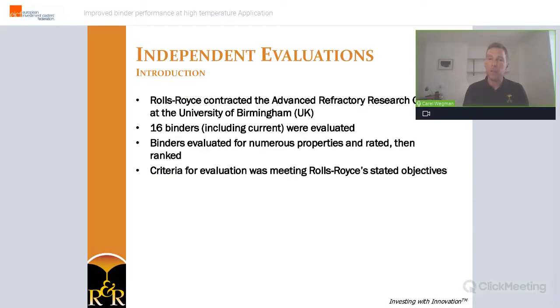So at this stage, we finalized all our in-house testing and we were comfortable that EHT would make a viable candidate for Rolls-Royce's new binder, and we submitted it. The next phase was driven by Rolls-Royce. They contracted the University of Birmingham to do an independent evaluation on EHT, but also on other binders that were submitted. In the end, a total of 16 binder candidates, including the legacy binder, were evaluated on different properties.